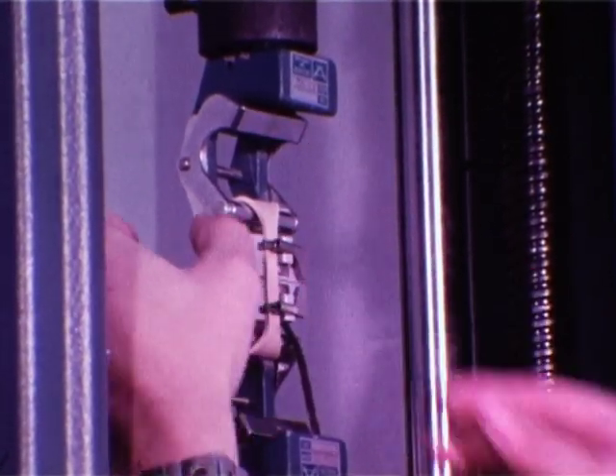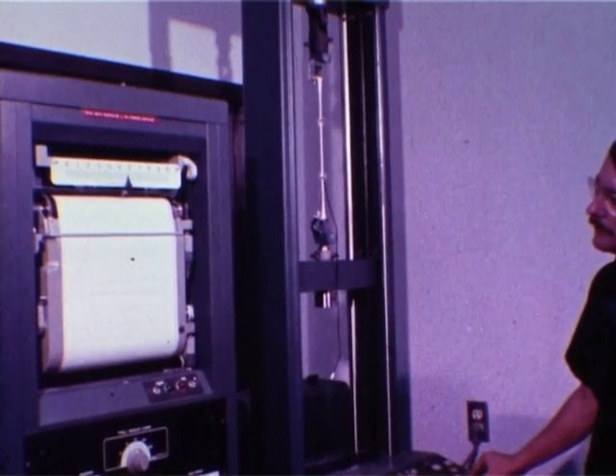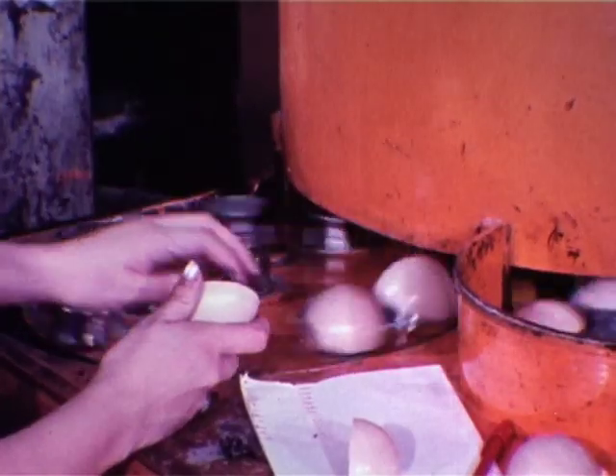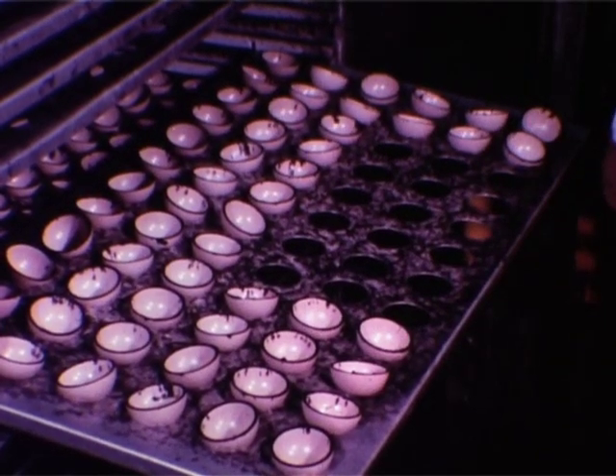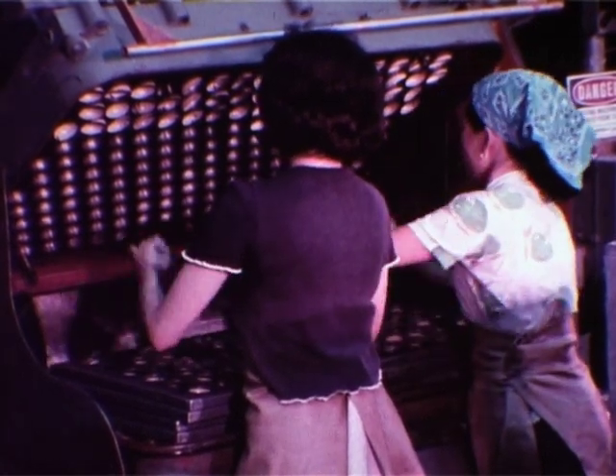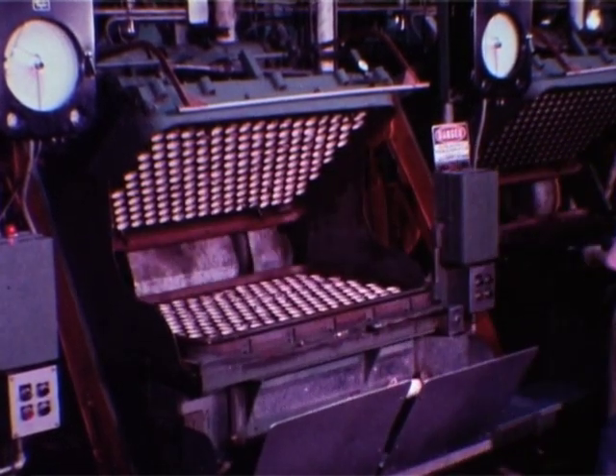In-line testing is constant and searching. This unique operation buffs the edges of the half balls precisely and carefully applies a natural rubber cement. Each half is ready for mating, ready to be sealed and vulcanized to form the center, the heart of the tennis ball. Another mold, different from the first, handles the second of the three cures. These molds are pressurized, which enables them to trap air inside the ball centers — approximately one atmosphere, or about 15 pounds per square inch.